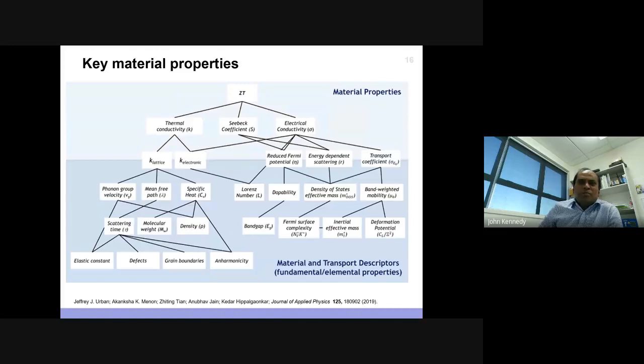Then people did a lot of work looking at the phonon group, which can influence the lattice thermal conductivity, and the specific heat. They then went down and did a lot of theoretical and experimental work to prove whether it depends on the elastic constants, or on the fundamental defects of the materials, or maybe the grain boundary effect, which can influence thermal conductivity. That's been heavily researched, and now we've reached the point that there's nothing much you can do, because we studied amorphous, crystalline, and polycrystalline materials.